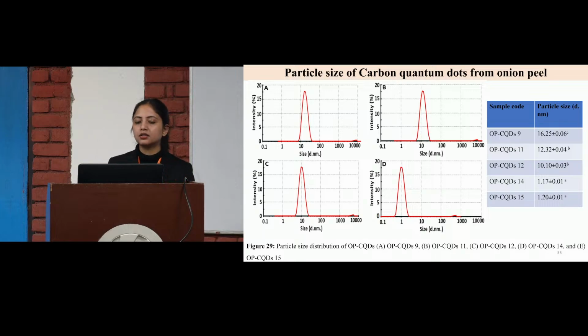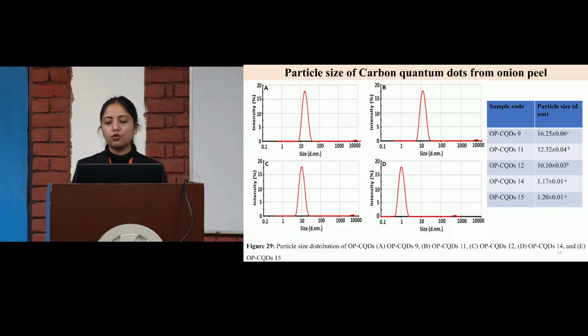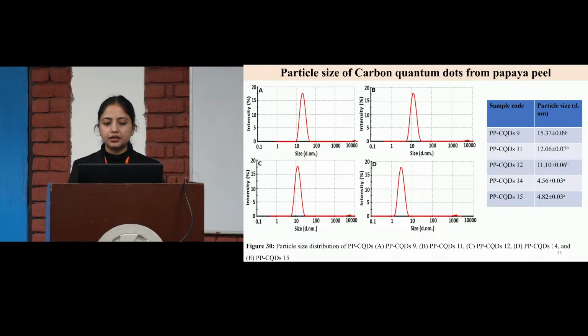Then the particle size of the carbon quantum dots, as I told earlier, is between 1 to 10 nanometers. At low time or temperature conditions, we got particle sizes of 16, 12, 10, but with the best optimized time or temperature condition, we got the smaller size of the carbon dots. As in the OPCQD 14 treatment, we got the 1.1 nanometer size. So this is the least particle size of the carbon quantum dots, derived from the onion peels.